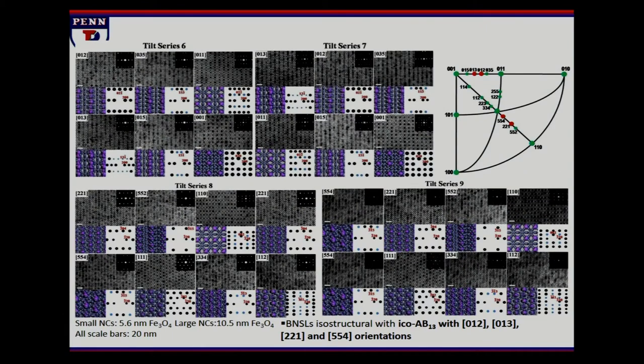So it's a very busy slide, but this is in the background that says, this is how we understand or assign the particular structure for any one of the other images that I'm going to show you, is that we've mapped it in 3D by taking the sample and tilting it and imaging it at each of the major axes. And to be fair, we don't do that with every sample.